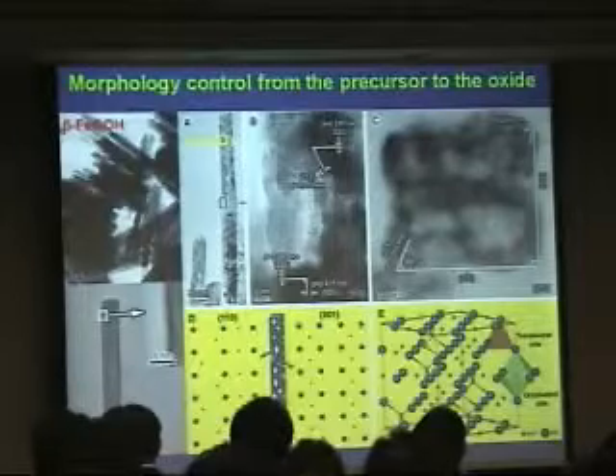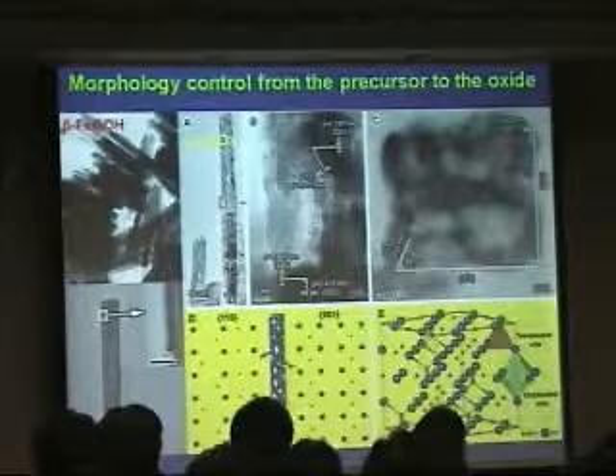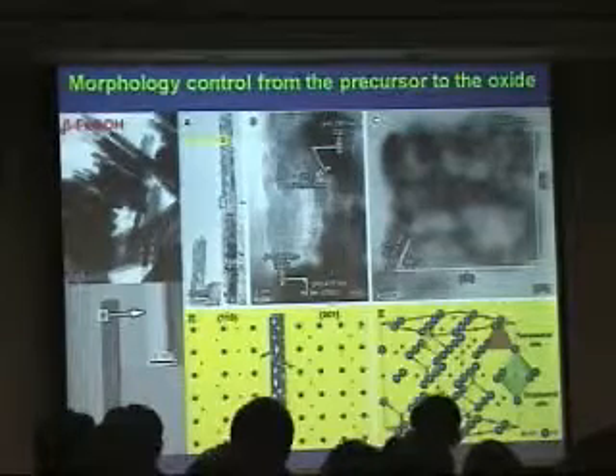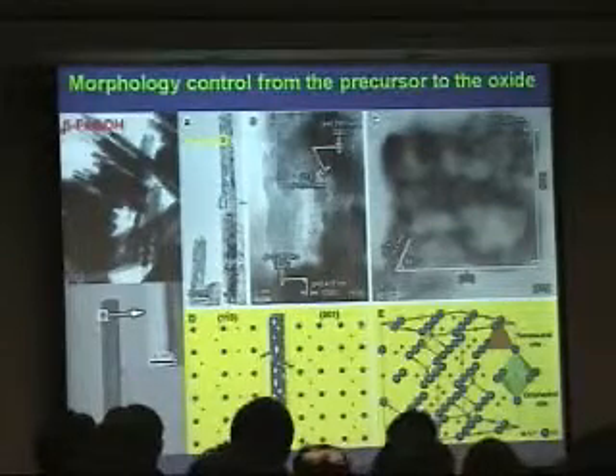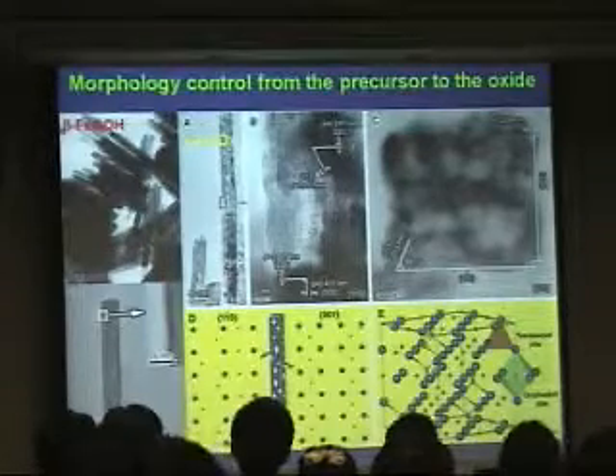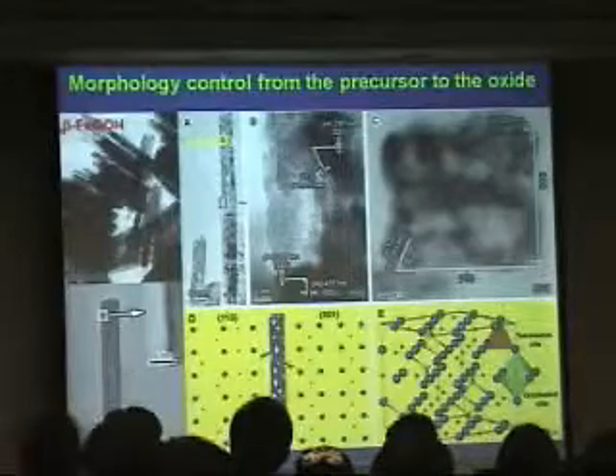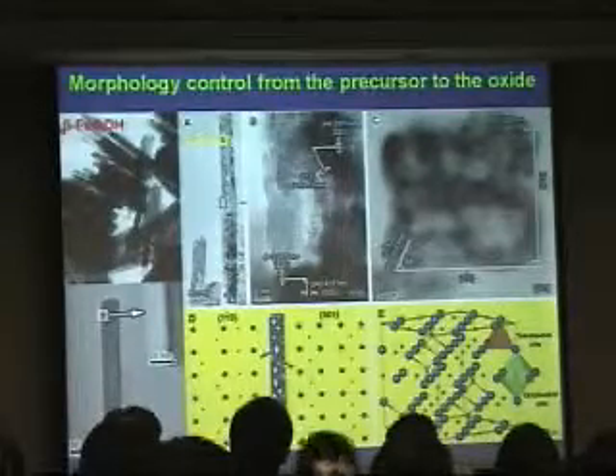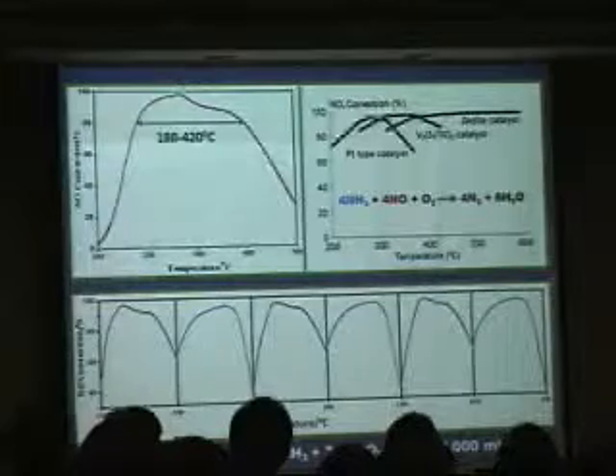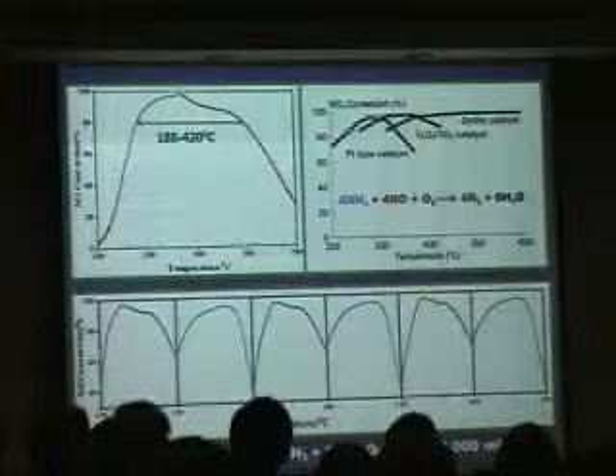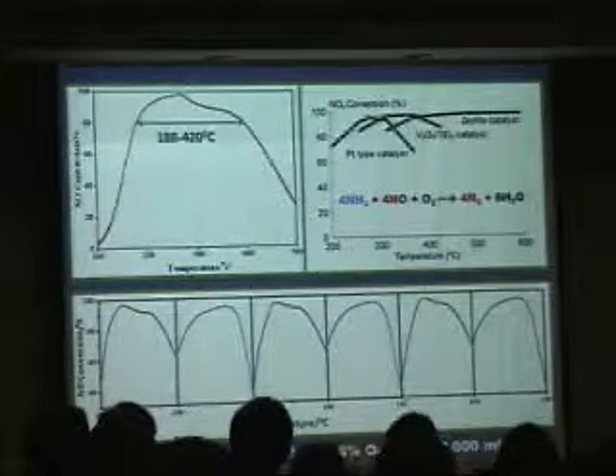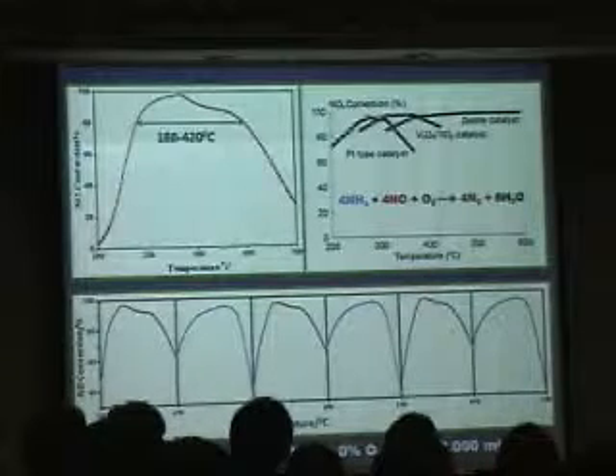feature seems like this. So the only advantage is that as this rod shape, usually for iron oxide, the iron is under the oxygen. But in this case, iron can be partially exposed, directly exposed to the outer surface. And then we use it for an important reaction. This is also typically used for the DeNOx process, as in the previous talks this afternoon.